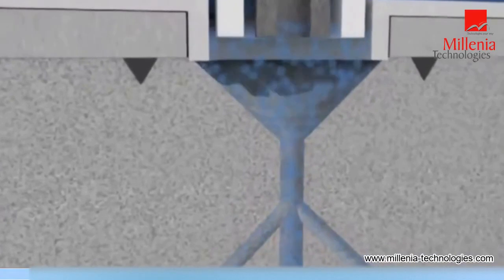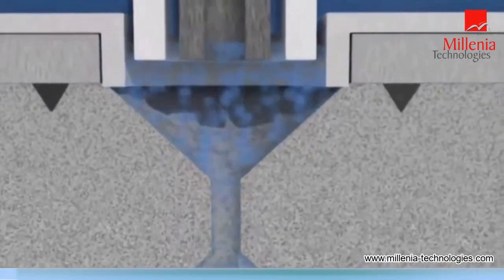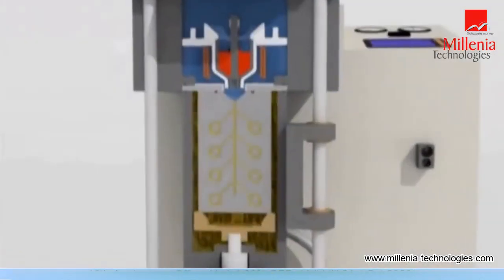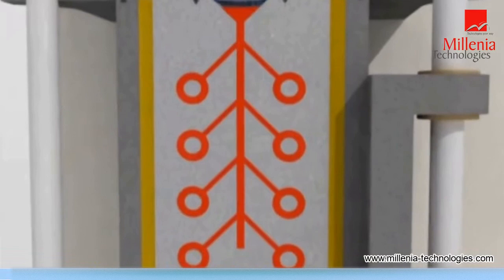This long-lasting system avoids the use of silicone gaskets or a flask with flange, with an important reduction in casting costs. The metal, once completely poured into the flask, is pressurized by argon up to four bars.